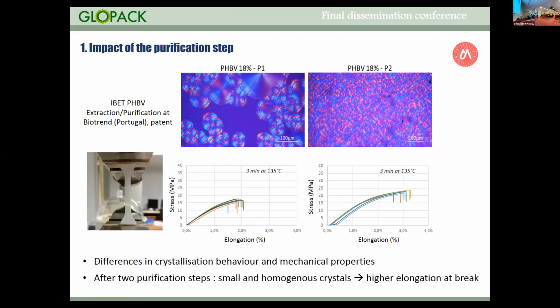And you can see on this picture that depending on the cycles of purification, the microstructure of the polymer is completely different. Here are pictures taken by polarized optical microscopy. After only one cycle of purification, you can observe very big crystals with some amorphous phase. And after a second cycle of purification, you have very, very small crystals and a very homogeneous structure. And when you characterize the mechanical properties, so it was a tensile test.